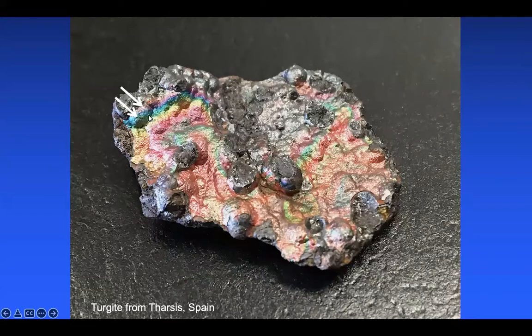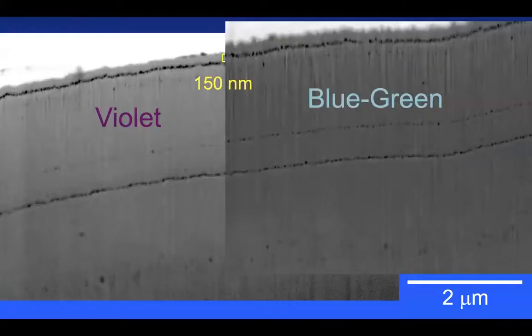I was curious to know, is there a difference in these void layers? And at first I thought the answer was no, until I put the two micrographs right next to each other. On the left is the section taken from the violet part of this Turgite, and on the right is a section taken from this blue-green portion. And you'll notice, fortuitously, we have two void layers that match up exactly, but this last layer right here is displaced by 150 nanometers. So again, it's just like that oil film on the water: we're changing the thickness of the film, and that is allowing us to access different colors in the interference that we see.